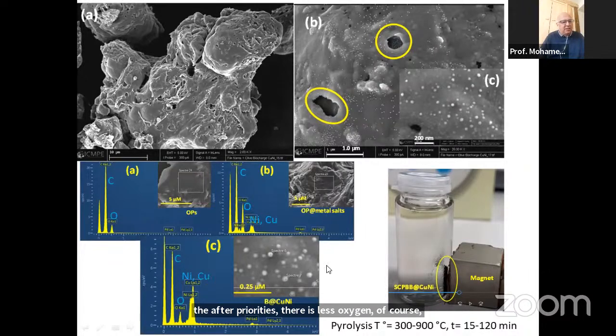And because of nickel, these biochar materials are magnetic and attracted by magnets, so we can collect them after any catalyzed reactions. Of course, if you load up to, for example, 10 times more copper than nickel, the final material, biochar with copper nickel, is not attracted anymore by a magnet.